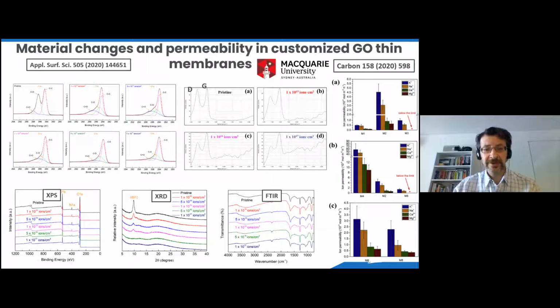Here we did detailed studies, and we fine-tuned the fluence, and we implanted or irradiated these membranes with the fluence in the range 10 to the 15, 10 to the 17. And depending on the fluence, you can see the changes in the structure and also the structural components, the changes in atomic bonds, or the surface characteristics of these membranes. And also on the right side, you can see the first top image, or the left characteristic, is the permeability of the non-irradiated membrane, and all the other characteristics are showing increase of permeability for different cations depending on the fluence or different treatment of these membranes.